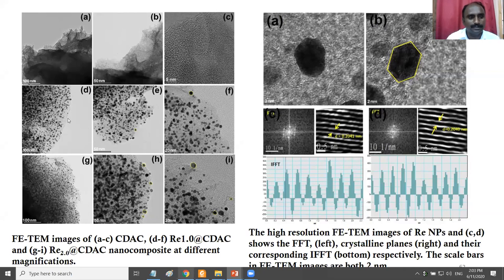So you can see the very, very small black dots indicating the rhenium nanoparticles. They are highly distributed on the carbon surface. That means the rhenium is highly distributed over the carbon. And also, this composite is highly conductive. That's why we are using it for two types of application: one is an electrochemical sensor, another one is an energy storage application.